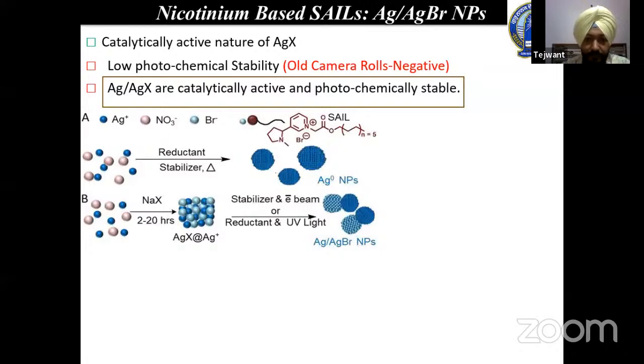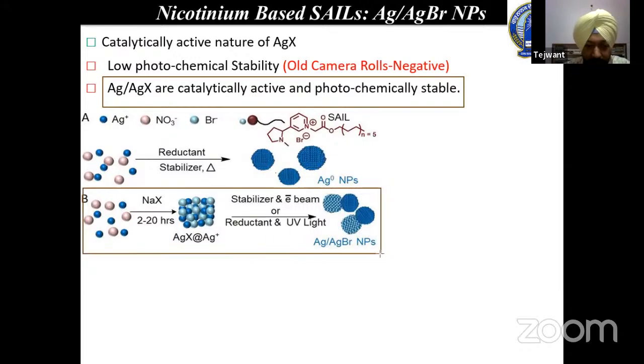In the conventional system, what has been reported before the publication of this work is that we have to take silver nitrate, and then add NaX, sodium halide, into that. And we have to keep the aqueous solution for 2 to 20 hours so that a crystal of silver halide having excess silver ions in its interstitial sites can be formed. Further, when we irradiate this crystal under an electron beam in the presence of a variety of chemicals which are called reductants or stabilizers, one can have silver bromide Janus nanoparticles.